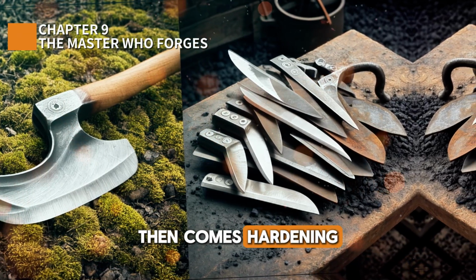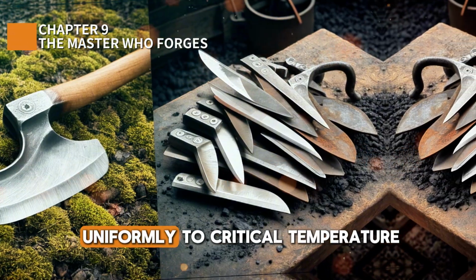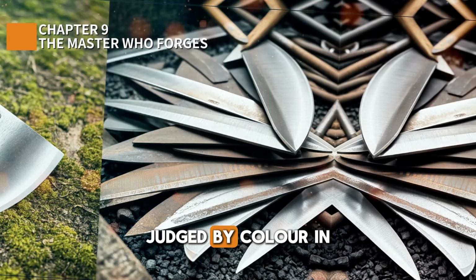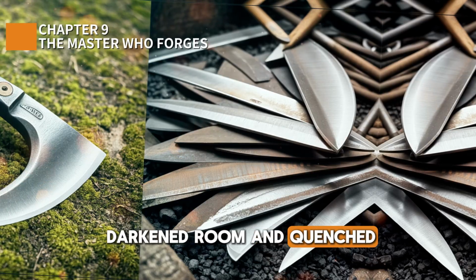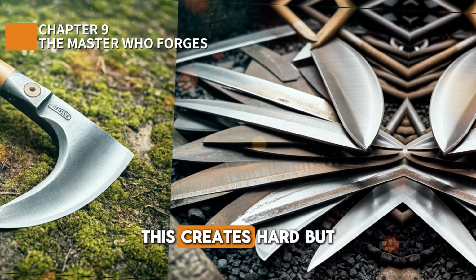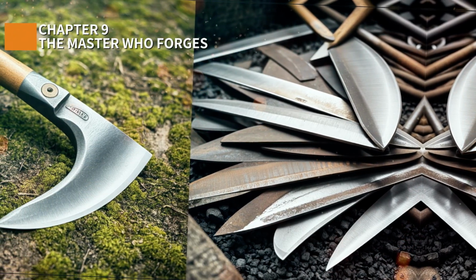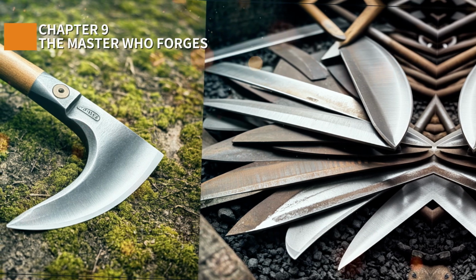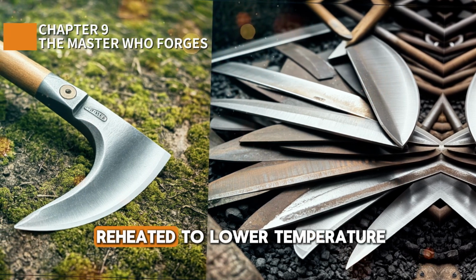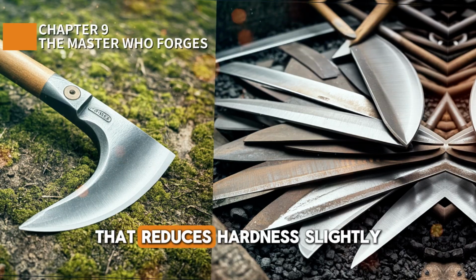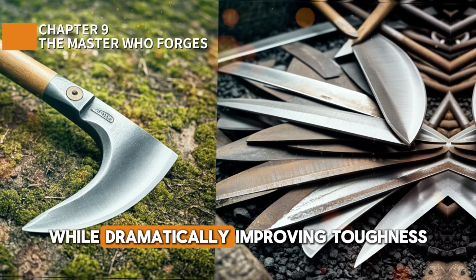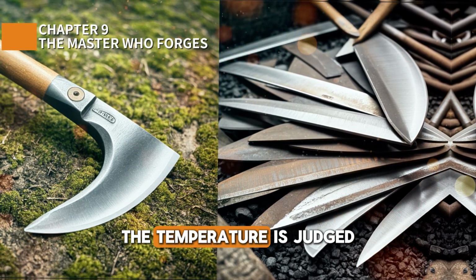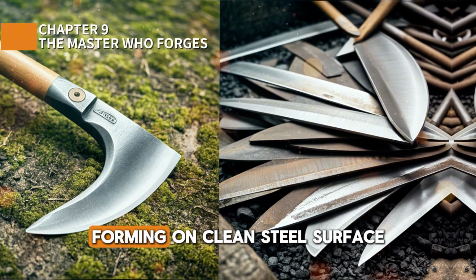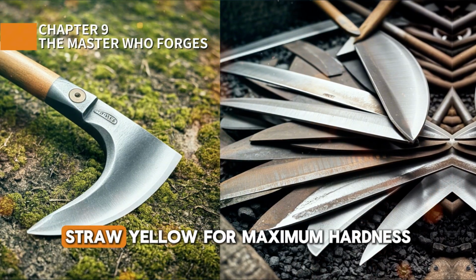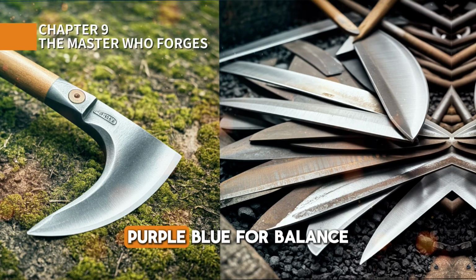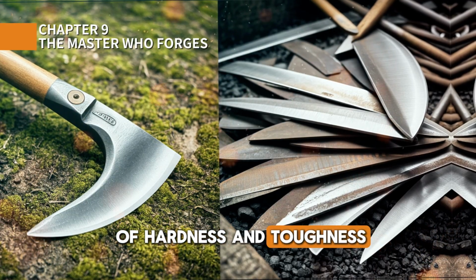Then comes hardening. The blade is heated uniformly to critical temperature, judged by color in a darkened room, and quenched in oil. This creates hard but brittle steel. Immediately after quenching, the blade is tempered, reheated to a lower temperature that reduces hardness slightly while dramatically improving toughness. The temperature is judged by oxide colors forming on the clean steel surface, straw yellow for maximum hardness, purple blue for balance of hardness and toughness.